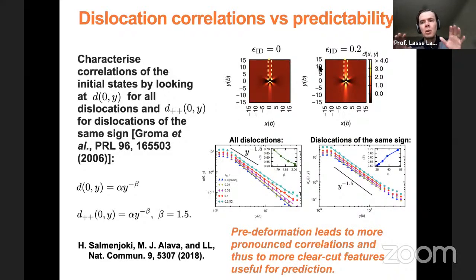Of course, if you had a completely random, gas-like, featureless initial state, then it would be difficult, I guess, to find anything that you could correlate with the stress strain response. But if there are clear features, some structures that you can clearly see if you look at the configuration, then it becomes easier for the model to predict. And indeed, we found that the predictability, especially for large strains where you have these structures formed already, was better for these pre-deformed samples where you have more structures.